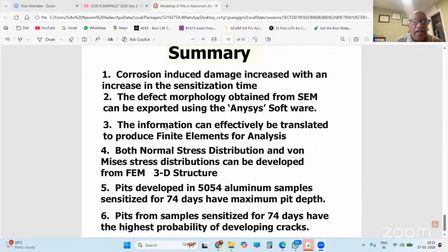And we can convert it so that normal stress and von Mises stress plots can be developed, and the fate of the pit as a function of time can be elucidated from this in the virtual world. So finally, we realized the two pits, sensitized for 74 days, have the highest probability of developing cracks. And that is what the FEM analysis predicted. And that is what we observed.